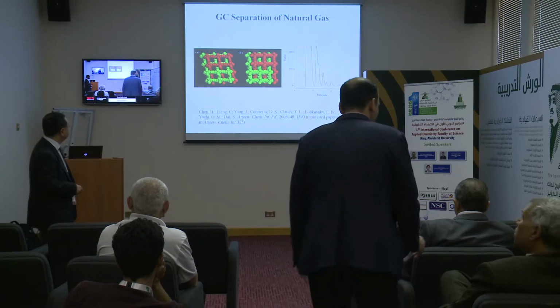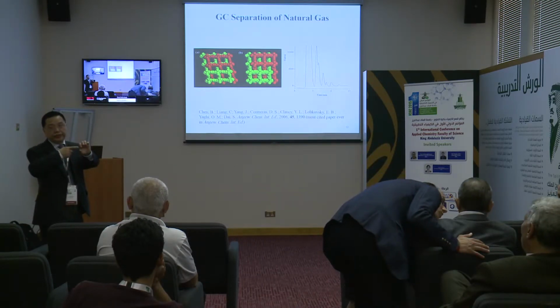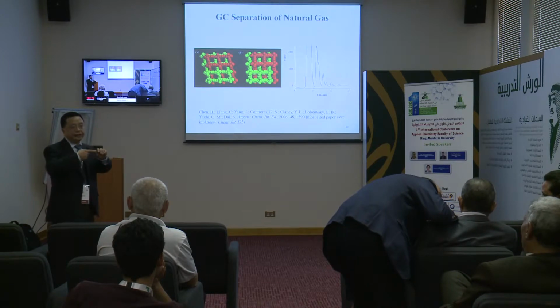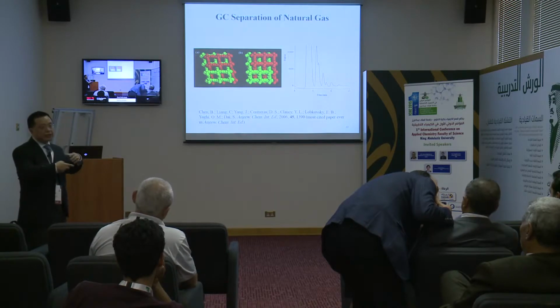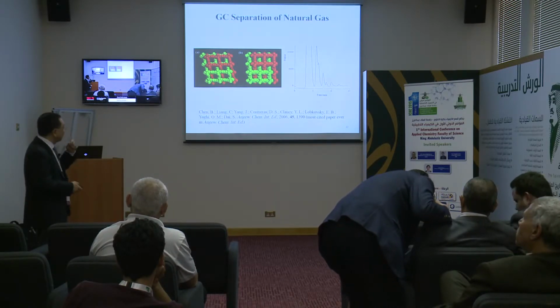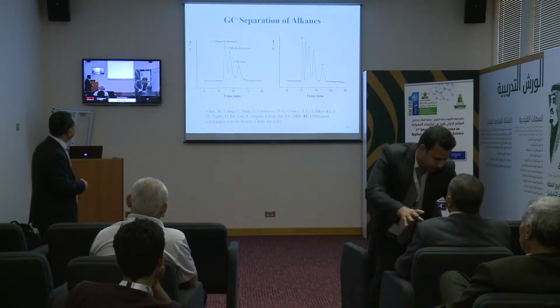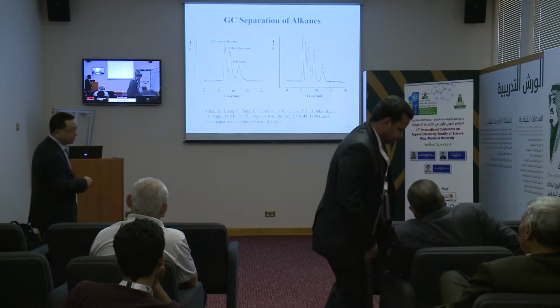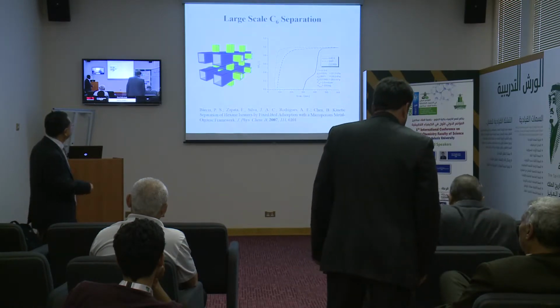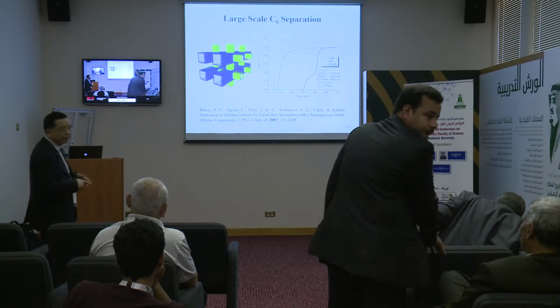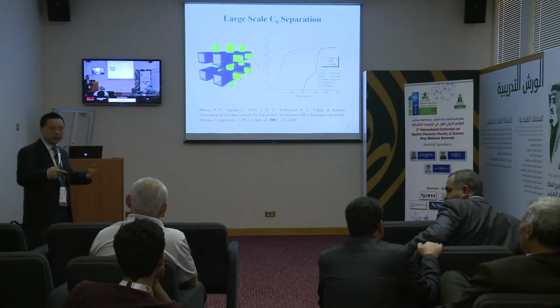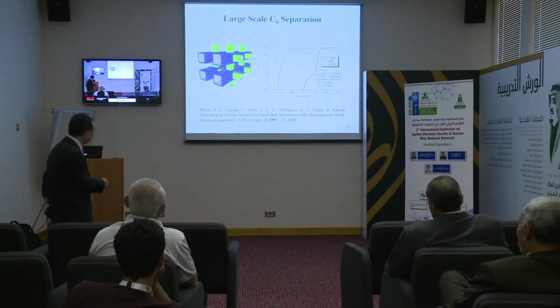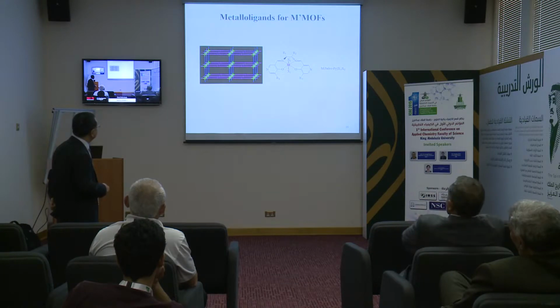Basically, the interaction strength depends on the length of the linear part. The longer the linear part, the stronger the interaction, and the slower this alkane goes through the channels, through the column. So this can also be utilized for separation of pentane isomers and hexane isomers. It is quite straightforward, and the separation can also be enlarged to fixed bed adsorption. Eventually we need to use a tower for separation. So very potential.